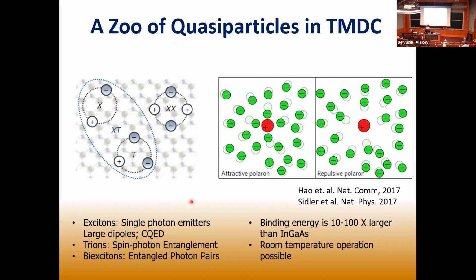And all of these species have been studied before for quantum information science. If you can study one exciton at a time, they will act like single photon emitters. And for this material, they have huge dipoles, meaning the dipole is just a quantity, r dot E. You integrate over the wave function. It gives you a quantity to characterize how strongly this entity couples to light. So a large dipole means they couple to light very strongly. For a thin single layer material, if you shine light resonant with the exciton, they absorb almost 10% of the light. That strong absorption also dictates that whenever you create an exciton, it tends to recombine very fast. How fast? This is the how fast is fast from early on in my talk, about 200 femtoseconds.